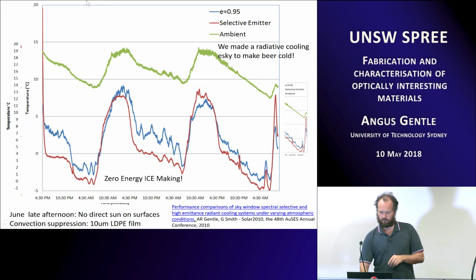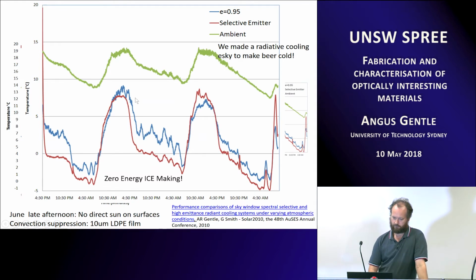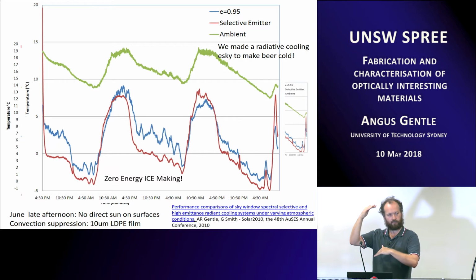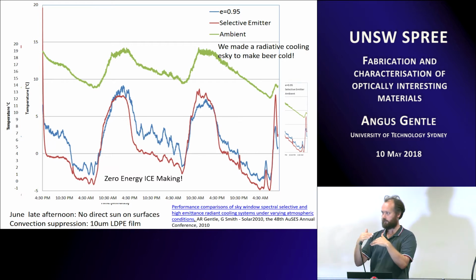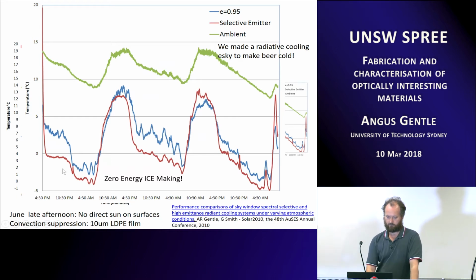So if you look at it over a couple of days, it stayed subambient the whole time. What you'll see here is that one surface was a black body, or 0.95 emittance. The other one was a selective emitter. So you can see the selective emitter is able to get colder than the other one because of the temperature regime we're operating in, where there's not much thermal load and we're significantly subambient. And so, yeah, this one stayed very cold. So overnight it stayed at 0 degrees. You're getting up to 10 degrees during the day.